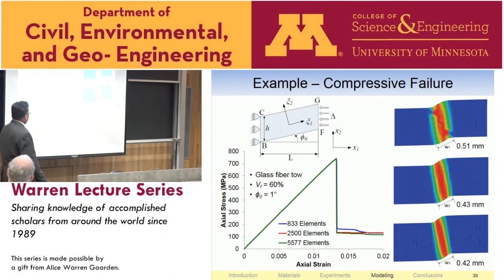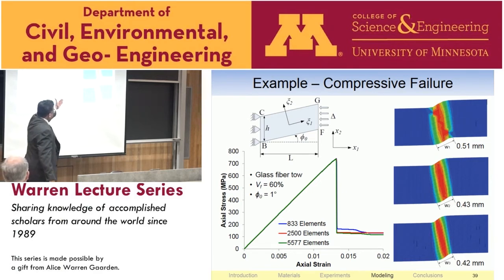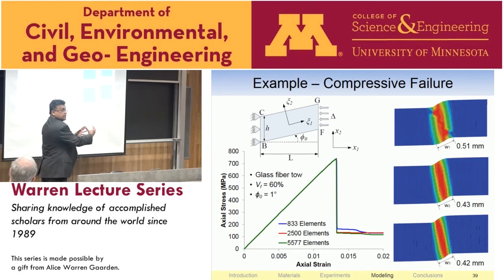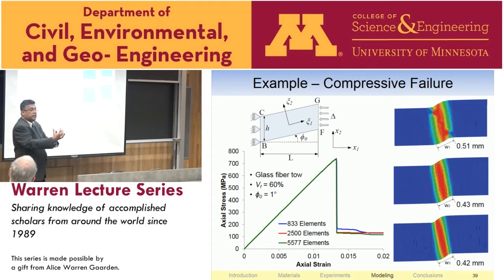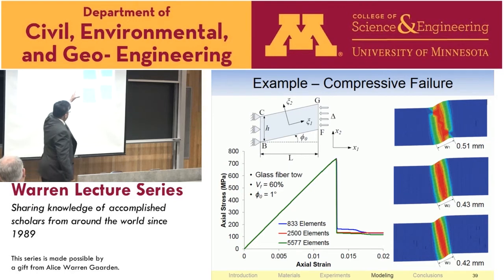Shear banding, right? So Diane Yoon developed, based on that multi-scale scheme I said, a method by which you can see not only is the shear banding mesh objective, but it's multi-scale, it's homogenized. So there's no fiber and matrix in this simulation, right? So it's a homogenized tow, right? But with the scheme where, at each integration point, we bring in the fiber and the matrix properties, and we run it. You can see that as we refine the mesh, the details of the band width and the angle of the band are preserved. So this is very advantageous for these calculations. We don't have to do the microstructural detail meshing. You can see that the calculations are mesh objective.